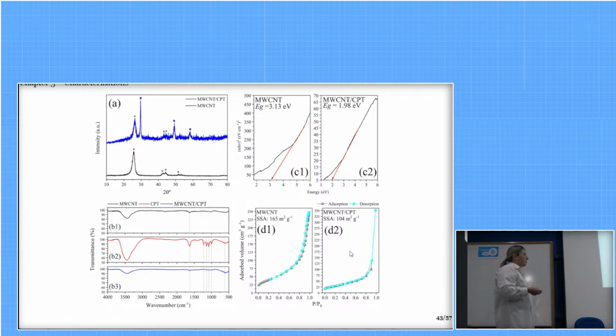The same patterns of preservation appear in the FTIR analysis, with a decrease in the surface of the multi-walled carbon nanotubes by incorporating the chalcopyrite particles. The most significant analysis here was the band gap analysis, showing a decrease from 3.13 electron volts to 1.98 electron volts in the copper.